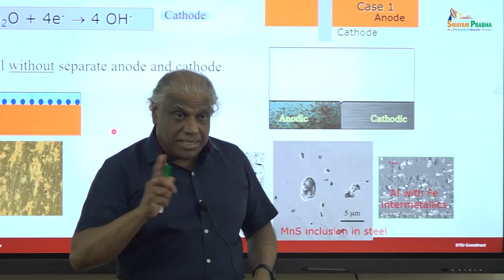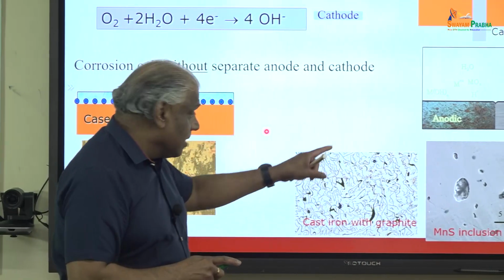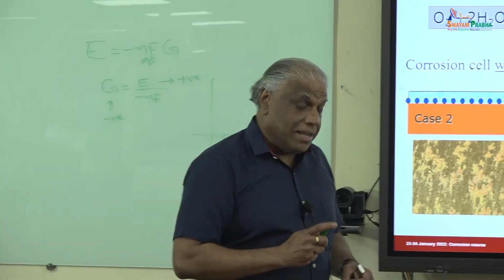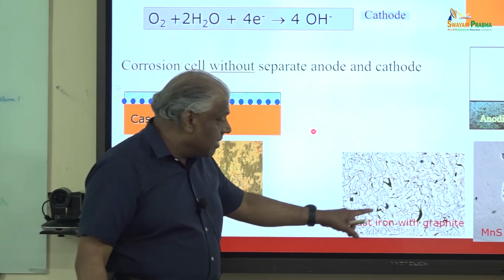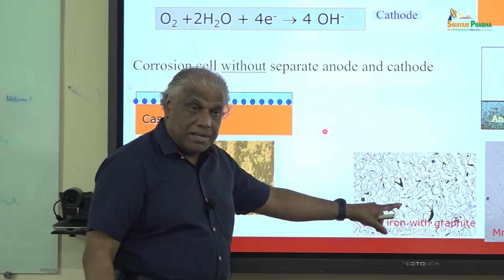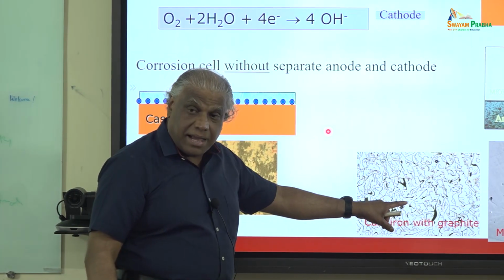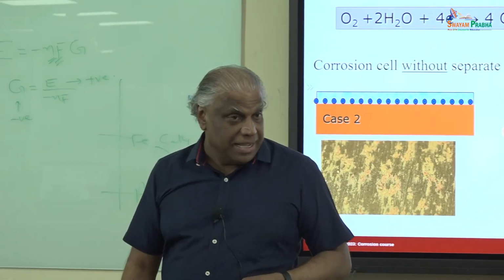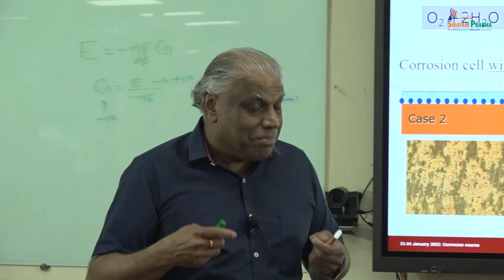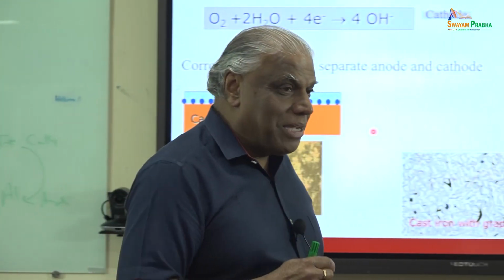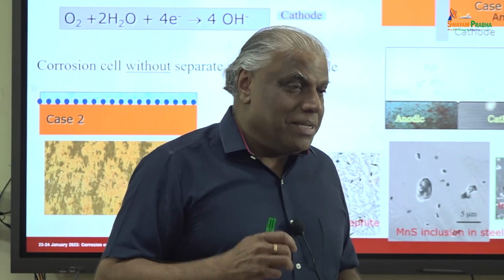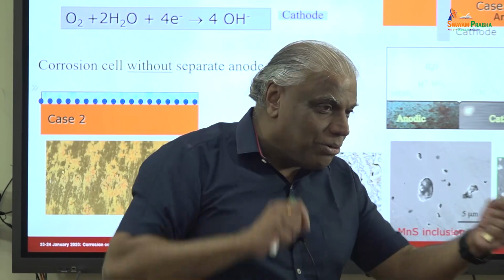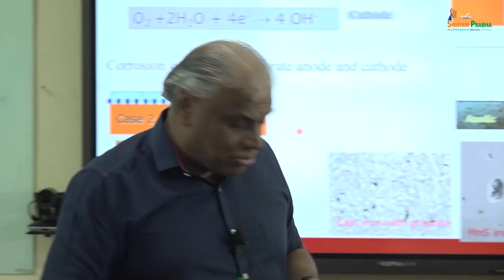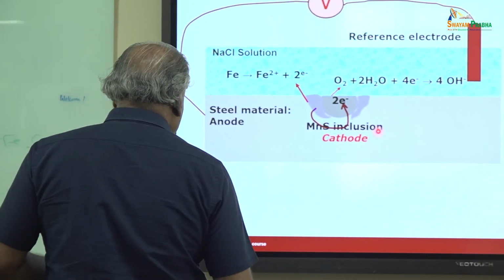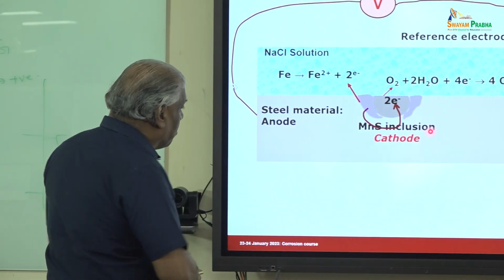So it's not necessary to have two different materials together. On the same surface, you can have different materials. In the case of cast iron, there is graphite and iron part. Graphite will act as a cathode, and the iron part will act as anode, like that. So this is the importance of the metallurgical microstructure. All metallurgical microstructures are heterogeneous, which means that automatically there is anode and cathode on the same surface, and that causes this corrosion problem. That's what I have schematically shown here.